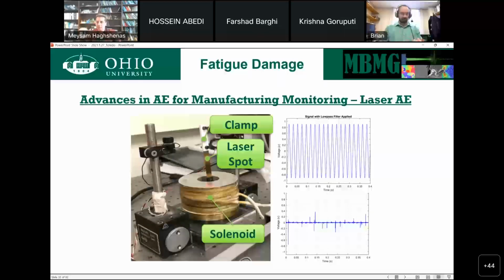Yeah. The only other issue with ultrasonic, I want to emphasize a difference with one of our methodologies. In ultrasonic fatigue, you have to design a very specific geometry because your sample is resonating. The methodology we're pursuing is actually building a spring that's going to resonate and treat the sample as a rigid body, so we can alter the geometry. The downside to that is right now we can hit 1500 hertz, so 1.5 kilohertz. We can't hit 20 kilohertz from that, but it gives us the ability to do different geometries.